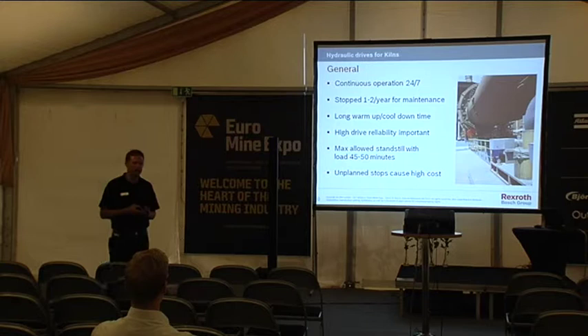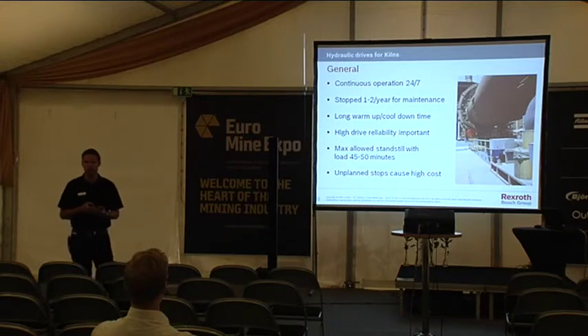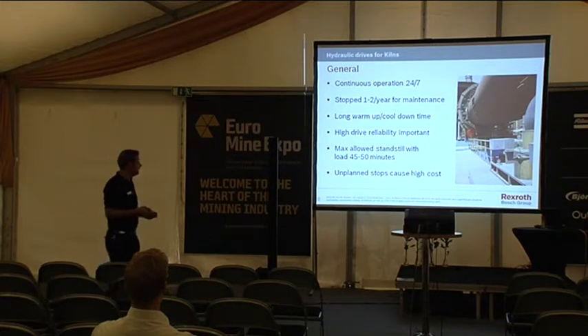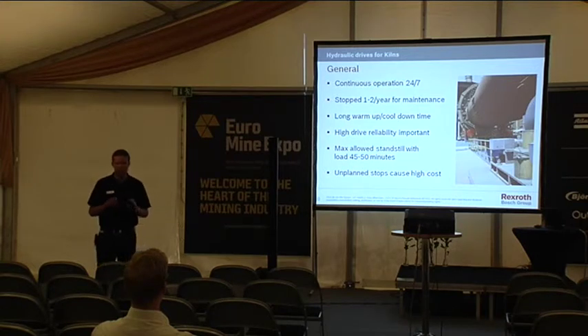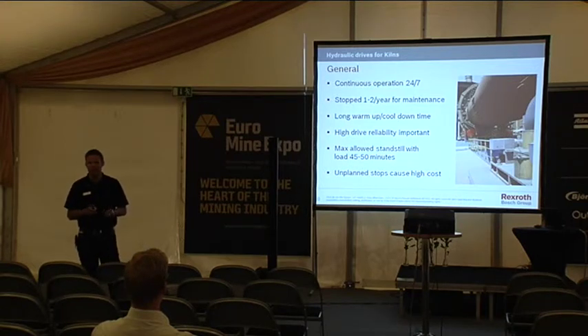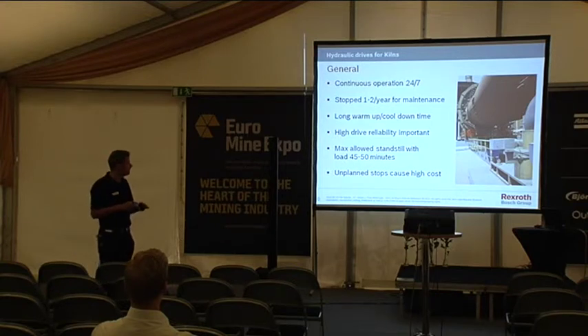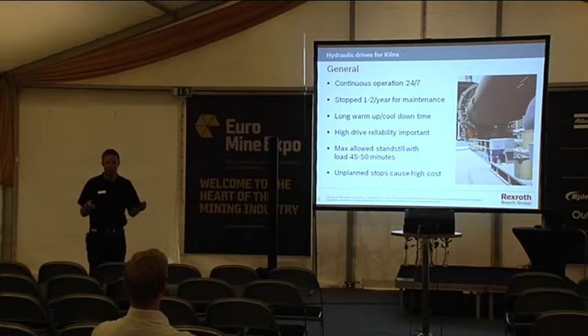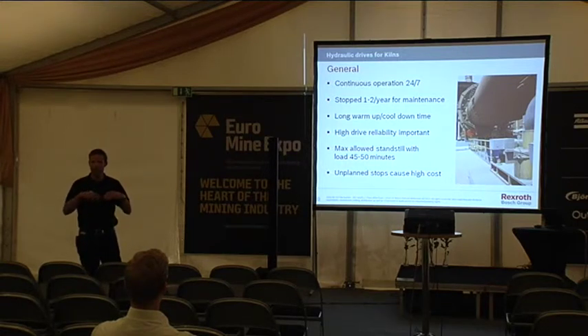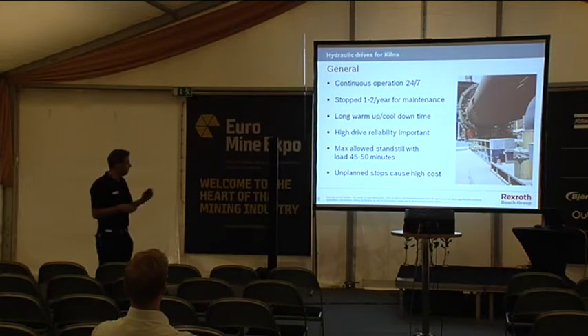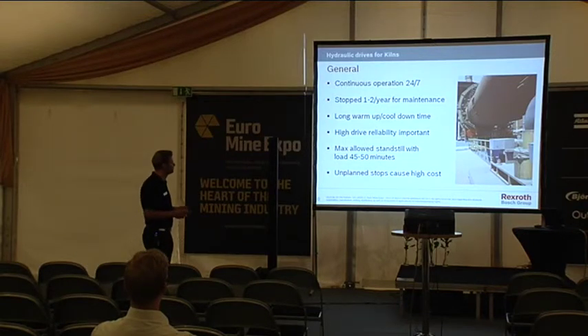You need to have high availability because every hour counts, and it costs a lot of money to stand still and lose production. And also reliability is very important, because if you have an unwanted stop, then it's very important that you can turn it, otherwise you will destroy the kiln completely because of the hot material. Either it will start to bend and look like a banana between the bearings, or it will eventually break. And that's why high reliability is so important.